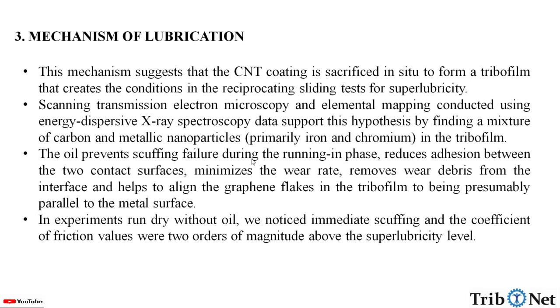The oil prevents scuffing failure during the running-in phase, reduces the adhesion between the two contact surfaces, minimizes the wear rate, removes the wear debris from the interface and helps to align the graphene flakes in the tribofilm, presumably parallel to the metal surface. So in these experiments, which were run dry without oil, they noticed immediate scuffing and coefficient of friction values that were 2 orders of magnitude above the superlubricity level.